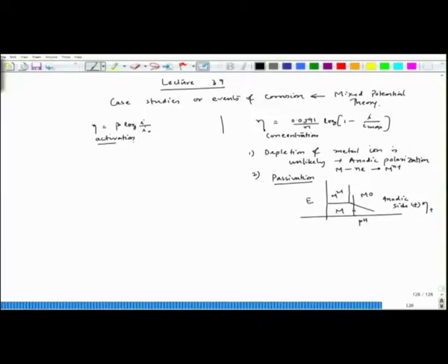Initially it is in the metal part, and then finally it goes to the metal oxide part. So metal oxide forms on the metal surface, which can lead to passivation. So at a large positive overvoltage there could be passivation, but the main reason is that depletion of metal ion is unlikely in anodic polarization.